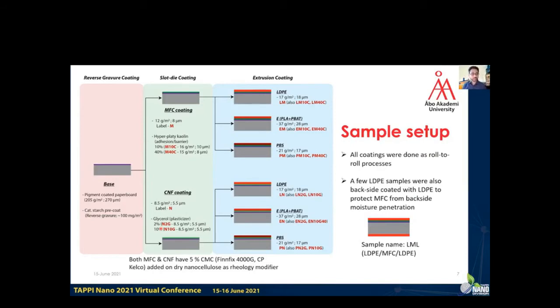And then we coat a thin layer of cationic starch to promote adhesion with the nanocellulose layer, about 100 milligrams per square meter, done with reverse gravure coating. Then we have a slot die coating of nanocellulose. As we said, two different kinds of nanocelluloses. One is MFC, done at 8 micrometer coating and labeled as M.